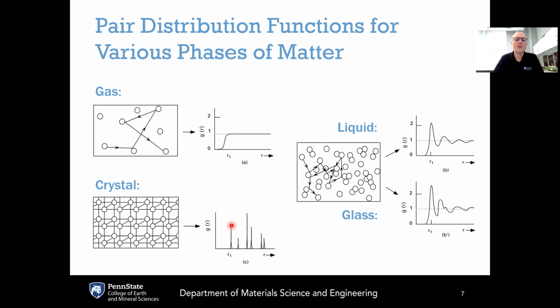So this gives you very sharp, well-defined peaks, not just at short distances and intermediate distances, but at long distances as well. If you have a perfect single crystal, then all the positions for all the atoms are always perfectly defined and perfectly well known, which would give you always perfectly sharp peaks here in the pair distribution function.